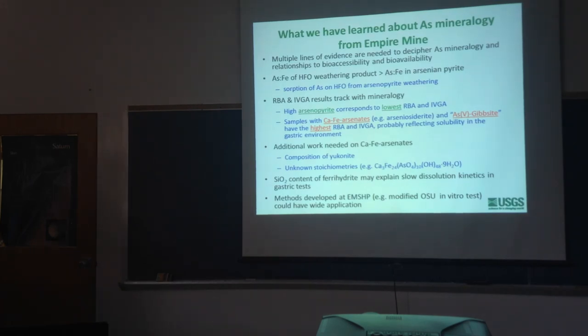We've learned it's complicated, that we need multiple lines of evidence to understand the relationship between mineralogy, bioavailability, bioaccessibility. We saw that the arsenic to iron ratio in the weathered products is higher than in the original pyrite. My main interpretation is that these rocks have arsenopyrite in them as well, so you're making iron oxide from oxidizing pyrite, and there's arsenic in solution that came from the nearby arsenopyrite grain, and that loaded even more arsenic onto the weathered product right around the pyrite grain.